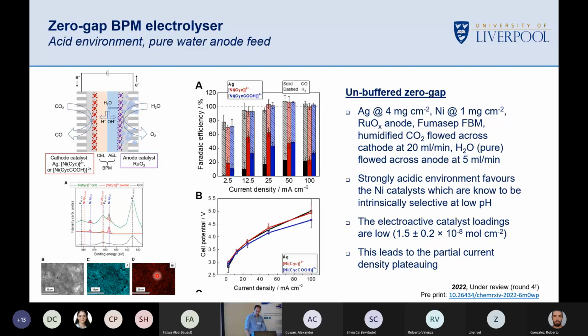And what happens when we run this thing? So there's a lot of data on this slide. So black is the silver catalyst. So if you look at A, there's the Faraday efficiencies. Black's the silver catalyst. Hashed is hydrogen. Solid is CO. And you can see that silver starts at low current densities with no CO being produced. And as we expect from sort of Mark's work, as we increase the current density for the device, CO Faraday efficiency starts to increase up to sort of 20, 30% at moderate current density. So we're at 100 milliamps per square centimetre now.